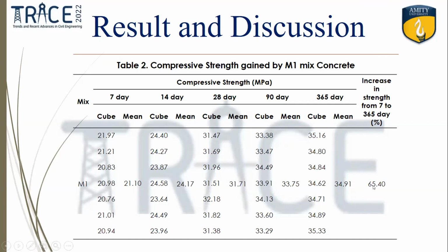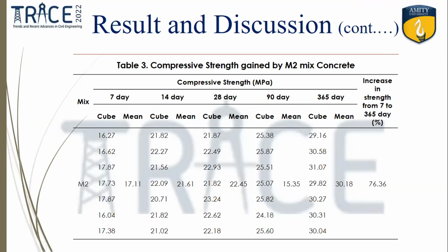This is what the conventional concrete gives us. Whereas if I see the M2 mix, that is the NaOH content having 10 moles, similar things were seen, but the increase in strength was 76%. Though the strength on the 28th day was less, I agree, if we require mixes for pavement constructions or block constructions, we can use this kind of mix, because some blocks have M10, M15 or M20 strengths. We can design it for the M30 mix and achieve M20, M25 strengths. But as you can see, as the curing days increase, the strength achieves the target strength.